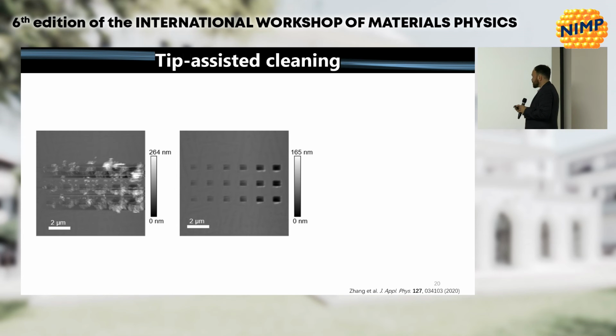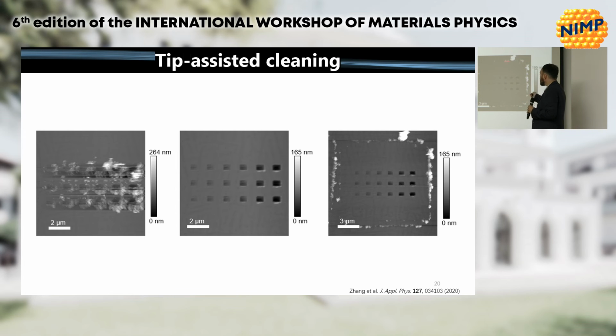It looks like that. If we do a slightly larger area, you'll see that we push the debris away. So now it's all around the edge. We didn't try this, but you might be able to clean this by some sonication or something. This was the approach that we used: machining with the forces that we wanted, then cleaning with a low force that we would normally use for contact mode imaging anyways for doing PFM, and then having a nice clean area.